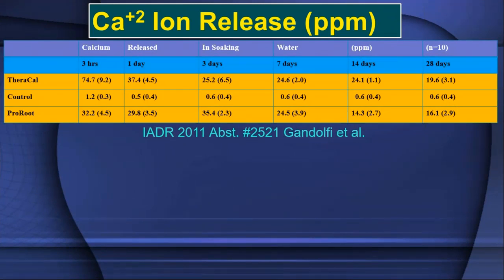And if you look at this chart, this is all from Gandolfi's research, all independent research, that actually TheraCal gives off more calcium than ProRoot MTA at 3 hours, even more at 1 day, less at 3 days, similar at 7 days, more at 14 days, and a little bit more at 28 days. So you see over a period of time, you get a lot of calcium release because the material is hydrophilic. It absorbs water and allows the tricalcium and dicalcium silicate to react just like it normally would.